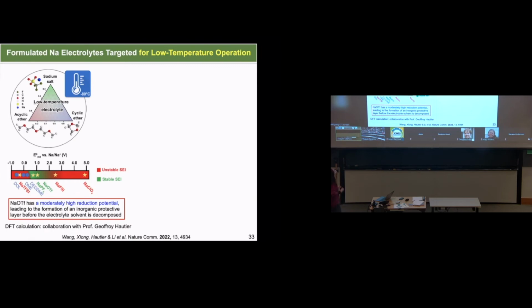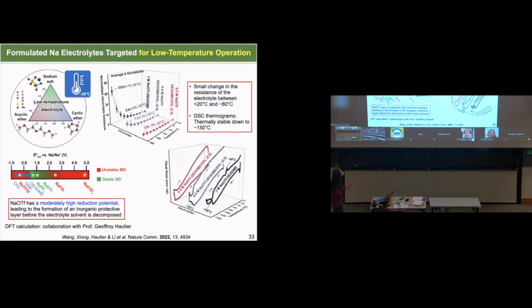We found this sodium salt by DFT calculation, combined with our experimental results, and it turns out that sodium OTF is a very good sodium salt when combined with two organic solvents, a cyclic ether and another ether. So we combine the two ether-based solvents plus the sodium salt, and we formulated an electrolyte that is thermally stable, as shown in this DSC graph, down to -150 degrees Celsius.